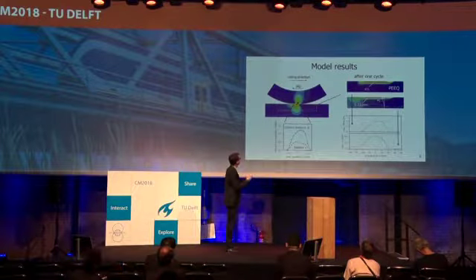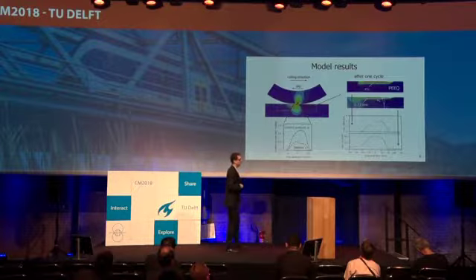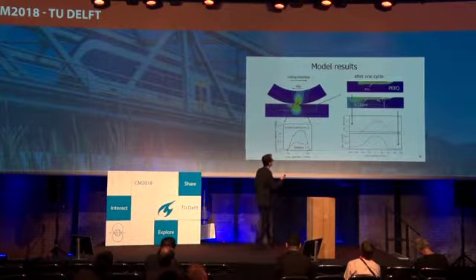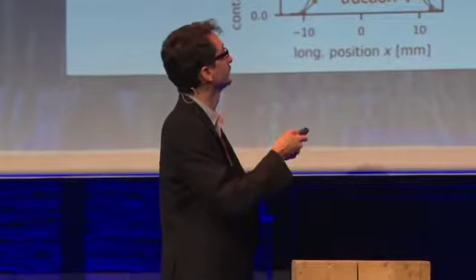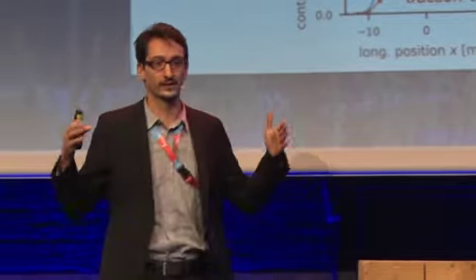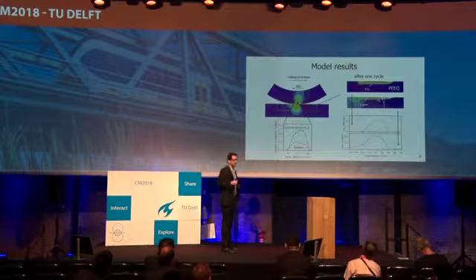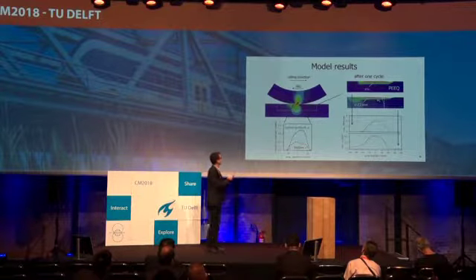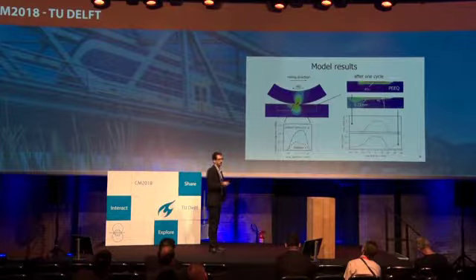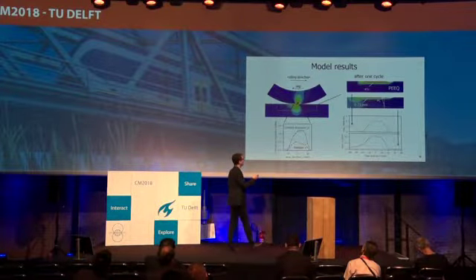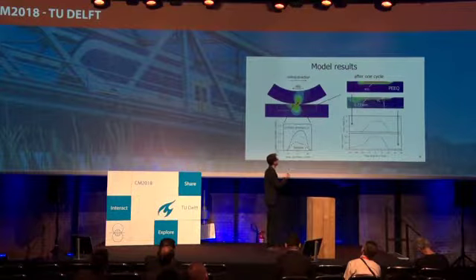And the other one would be, we take this part of the rail, and then we look, after one cycle, how much accumulated equivalent plastic strain is there. In this case, it's 4%. And it's quite uniform over the distance, or the rolling length. The next thing is, how much displacement in the longitudinal direction is there. We have an accelerating wheel. That means that we have some shear displacement in that direction. And in this case, we have a maximum shear displacement of 0.23 millimeters after one cycle.